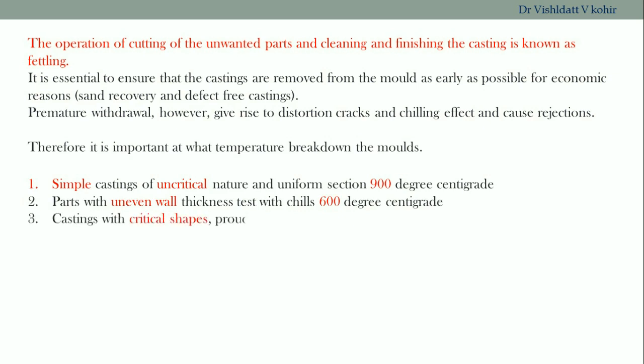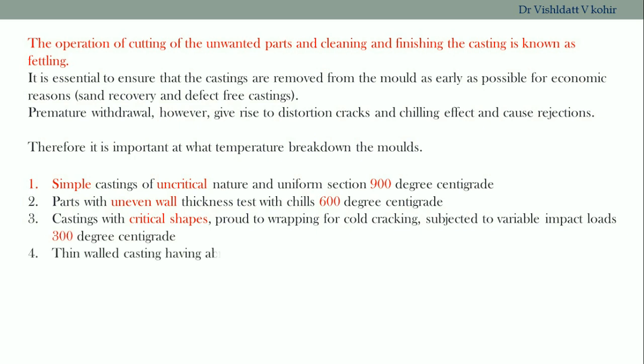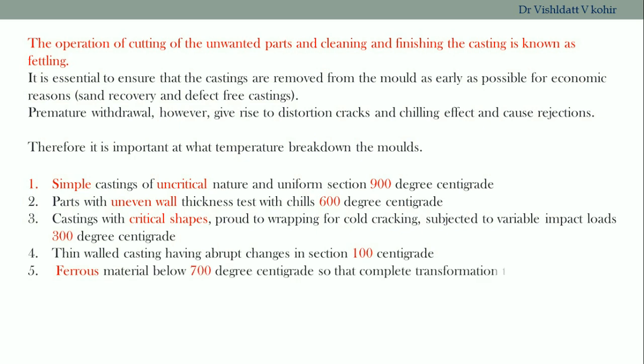For simple and uncritical types of jobs, 900 degrees centigrade is recommended. If the parts have uneven walls, then it should be carried out at 600 degrees centigrade. If the casting has very critical shapes and is prone to warping or cold cracking, then it should be fettled at 300 degrees centigrade. Thin-walled castings are fettled at 100 degrees centigrade.